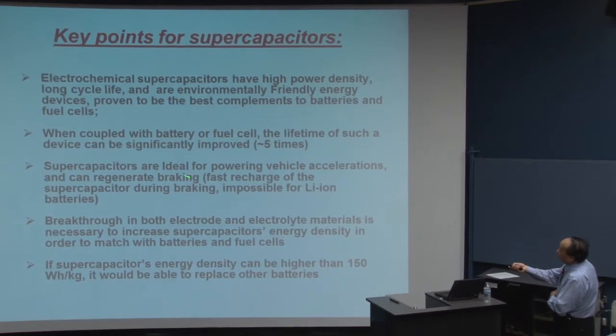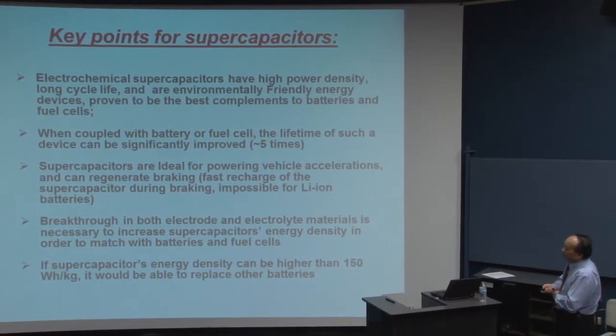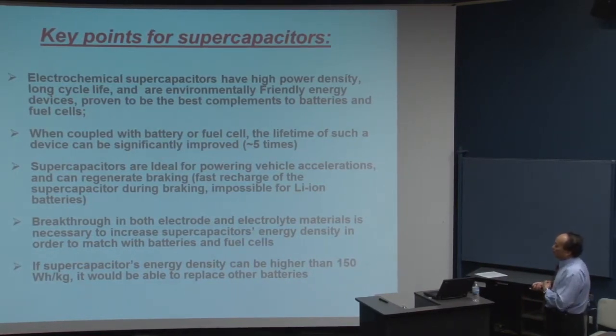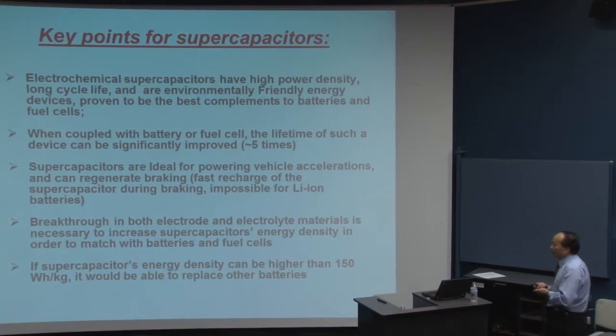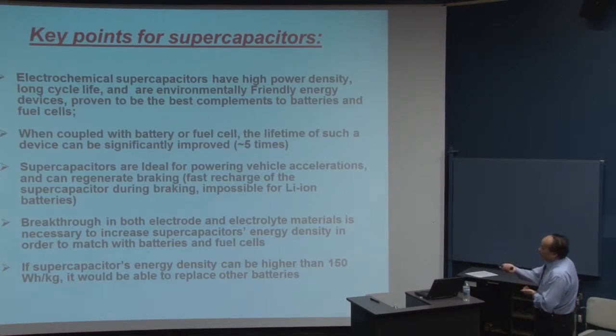The supercapacitor is ideal for power, like vehicle acceleration, and also for regenerative braking. And this is impossible for the other batteries, like the lithium ion battery, right? Another thing is that a breakthrough in both electrode and electrolyte material is necessary at this moment to increase the supercapacitor energy density in order to match the battery or fuel cell. If the supercapacitor energy density can be higher than 150 watt hour per kilogram, it will be able to replace other batteries. That's the direction and also the hope for the supercapacitor. That's why in the recent 2 years, supercapacitor research and development has been getting very high, at the cutting edge of research.